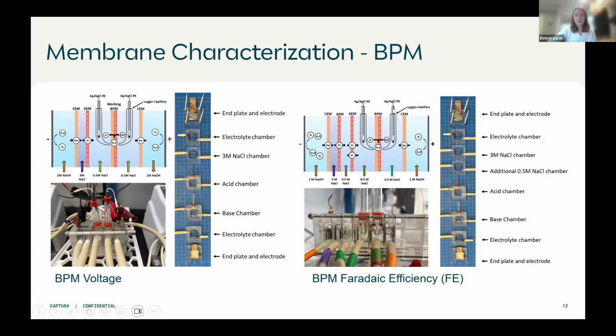For these cells, we've actually added an additional channel. We want to make sure that we collect all acid, or in the case if we're looking at the base, all base that is produced by this membrane, and we're not, again, losing any due to these leakage potentials across the AEM and CEM. Again, this is to evaluate just what the bipolar membrane itself is doing. When we look at the full stack, we actually look at the system more holistically.